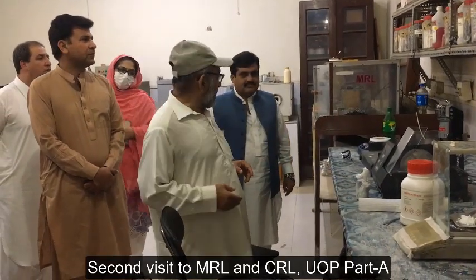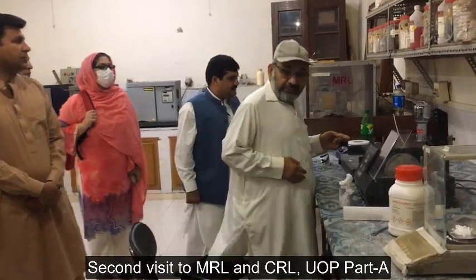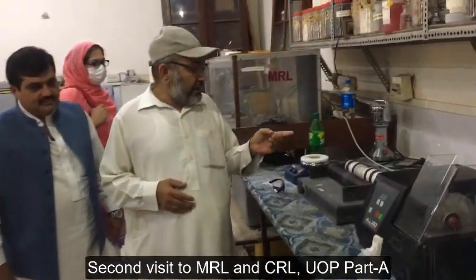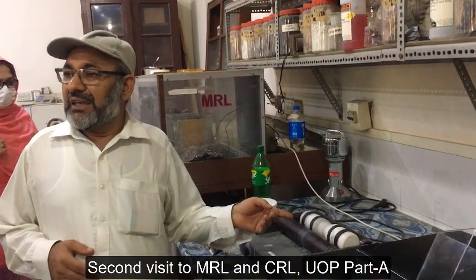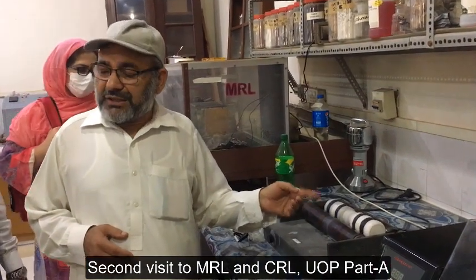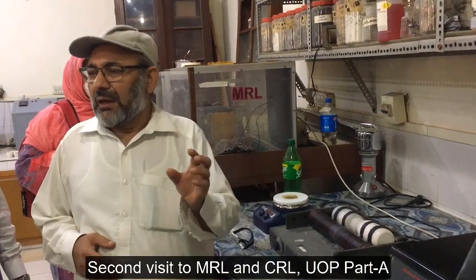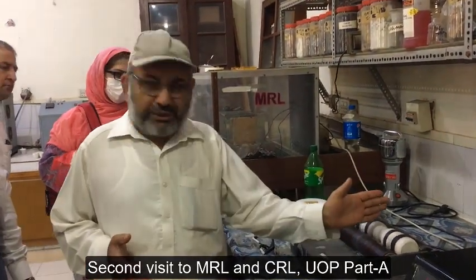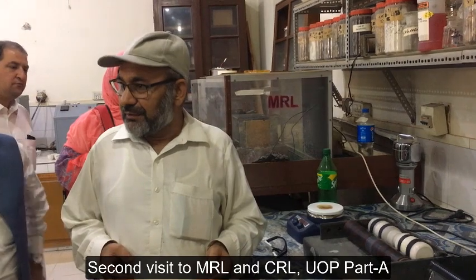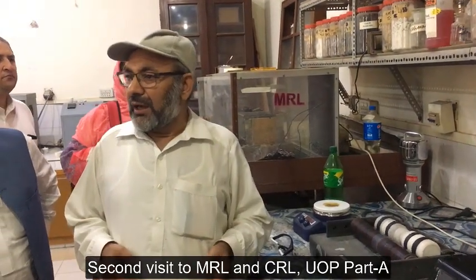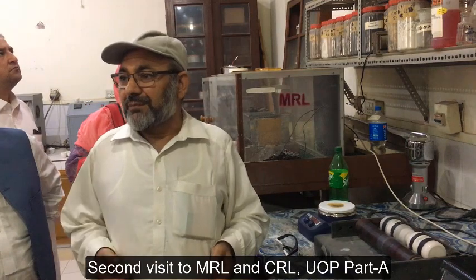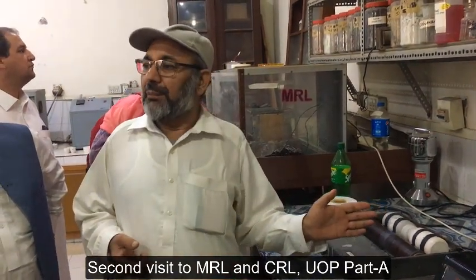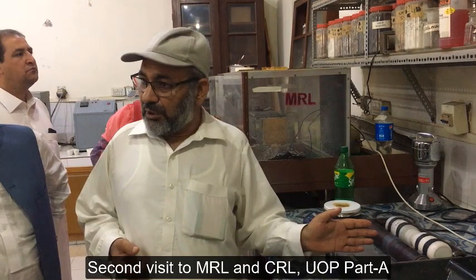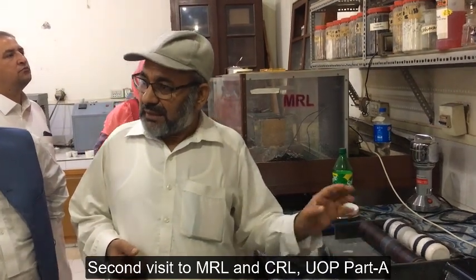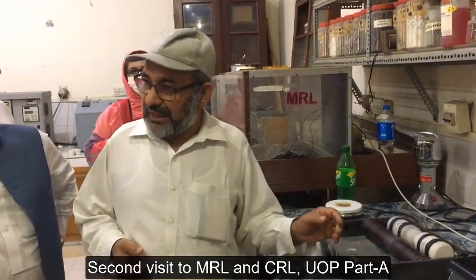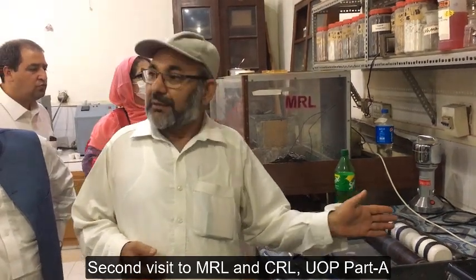Then when we take that, we bring these here. These are disposable milk jars. These disposable milk jars contain about a quarter of their volume of grinding media, which is usually zirconia or tungsten small balls. About 1/3 of acetone or propanol or distilled water, whatever we need for the mix milling of that material, and then the powder.